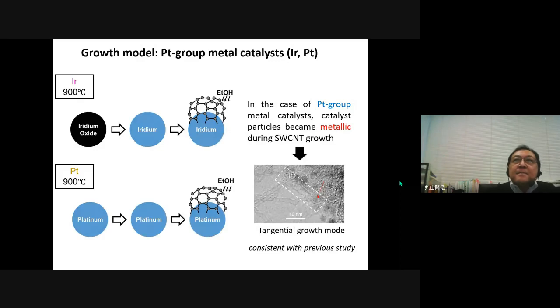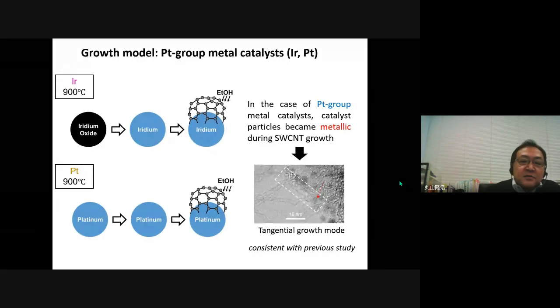Next, please. In contrast, for the platinum group elements, iridium and platinum, the catalyst particles were metallic during nanotube growth. It should be noted that TEM observation showed a tangential growth mode for nanotube growth from iridium catalysts. This result is consistent with previous prediction. Next, please.